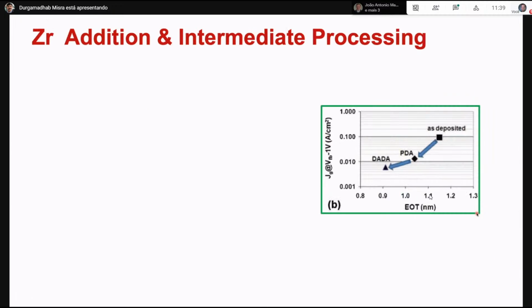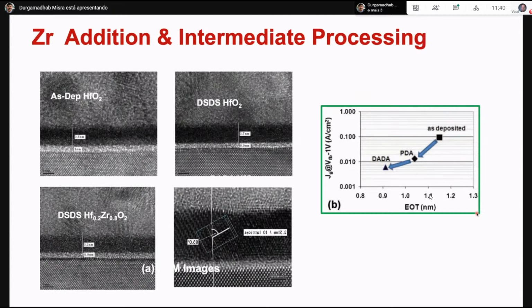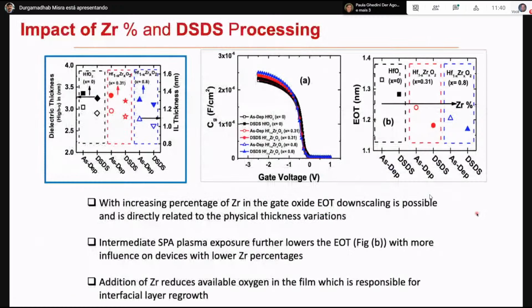So you thinking about this, we started with the idea of DADA that I mentioned. If you do simple PDA, as let's say you take as deposited film, whatever the leakage current you have, if you do a post-deposition annealing or PDA, then the leakage current goes down. And then if you do post-deposition annealing, deposition annealing, like a cyclic process, the leakage current goes down further. So you can make actually DADA or DSDS samples. You can create plain hafnium oxide or hafnium zirconium oxide with different zirconium percentage. That sort of things can be created in this. So we looked at some of those devices. It's because of the plasma exposure, the film become densified.